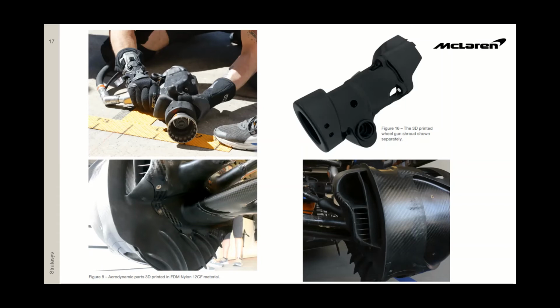Even so, at the bottom here, you can see some aerodynamic parts, end use, that go around the track on the F1 cars as well. So to give you an idea, you wouldn't typically use FDM maybe because you think it's not fully isotropic, it depends on the orientation. We can control the rasters, the way the rasters are laid down. So we can do alternating rasters like when you would lay down carbon fiber. Same sort of methodology here when you're processing the parts. Looking at the loads, the forces that are applied will allow you to do some very funky end-use parts that can be used.